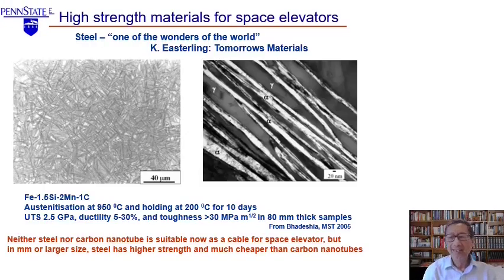Take steel. Take carbon, manganese, silicon, steel of this composition. Okay, 1.5 silicon, 2 manganese, 1 carbon. If you heat it to 950, hold it there to make a particular phase that we call austenite, and then put it in a pizza oven. And yes, you heard it right, a pizza oven that can give us about 200 degrees Celsius for 10 days. So cook it like we cook pizza, but for 10 days.